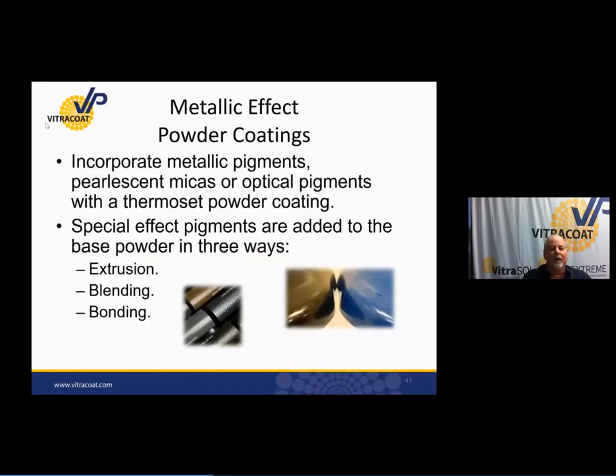There's a number of ways to introduce metallic into powder coatings. You can extrude the metallic, you can dry blend the metallic, and you can bond it. You can get some looks in blended metallics that you can't get in bonded materials. You can get some looks in extruded materials that you can't get in bonded. The reason for the bond is because what we're trying to do is protect the metallic, encapsulate it into the resin so that we get an application window that's broader.